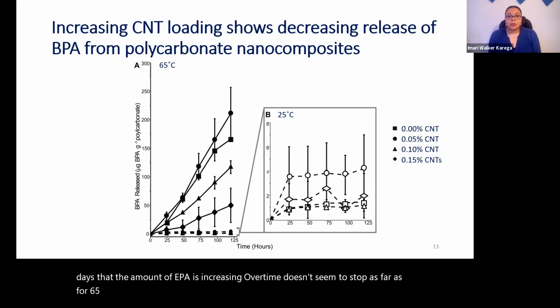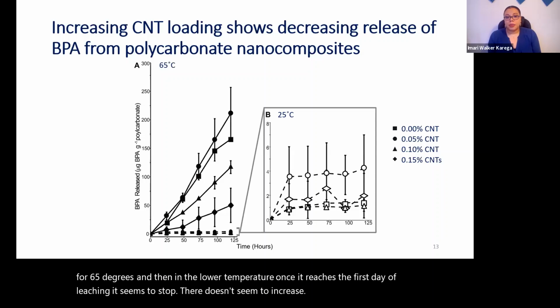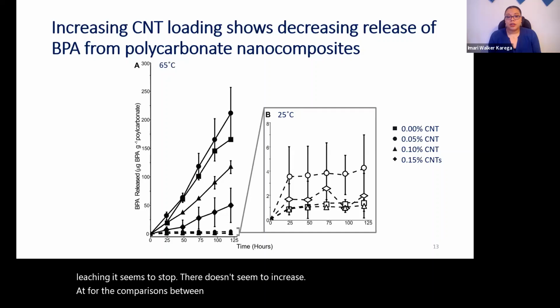At lower temperature, once it reaches the first day of leaching, release seems to stop and not increase further. Comparing the amounts, there's a significantly higher amount released at higher temperatures.